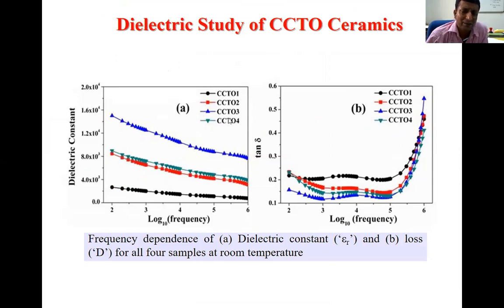Intentionally we produced it, and first we did the characterization, we were seeing the material having the secondary phase was showing better dielectric properties. And then we have done the analysis, and we came up with the reason also. There is this internal barrier layer capacitor model, under which we can see how we can account for the better dielectric properties with this secondary phase.